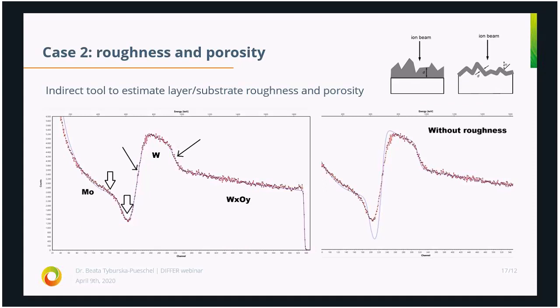Initially, the porous tungsten layer was flat. Only the molybdenum substrate had a little bit of roughness. But due to the exposure to Magnum plasma, the porous tungsten layer also became rough, with a different degree of roughness than the molybdenum. And so I was able to measure this roughness and the porosity.